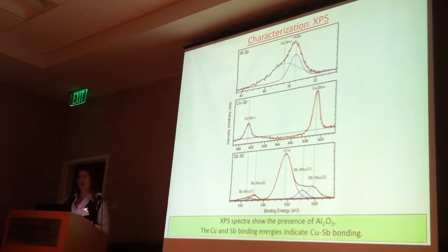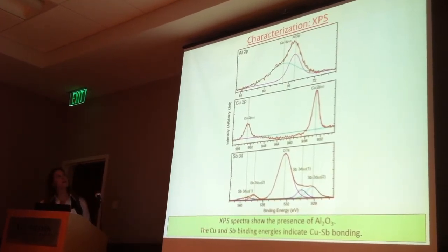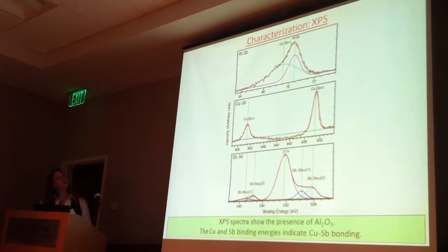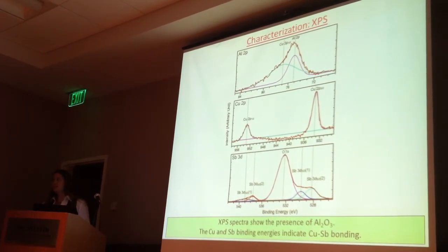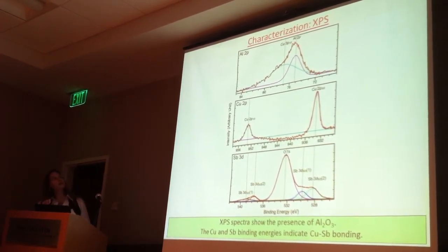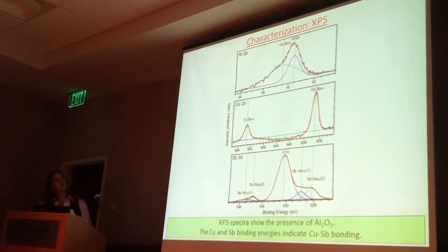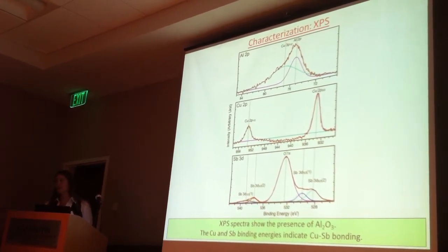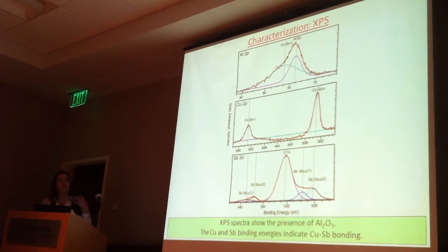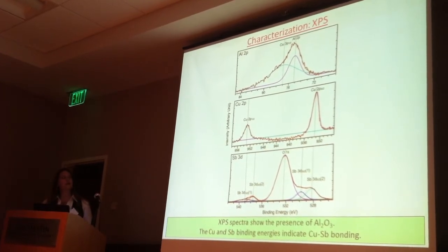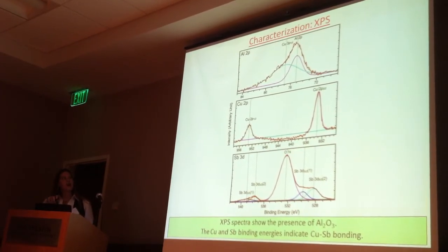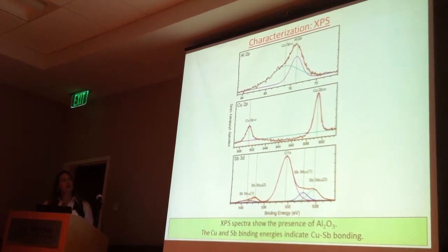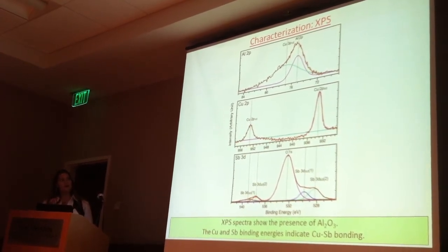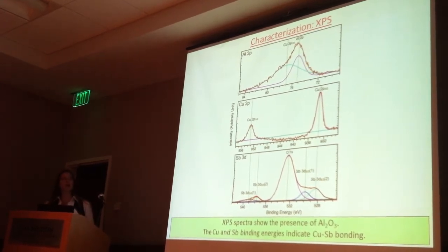So we turned to XPS, and this top graph here is the aluminum spectra for XPS, and this peak right here is for aluminum, and the binding energy does correspond to aluminum oxide. So we found, yes, we do have aluminum oxide in our material. And when we looked at the spectra for copper, we found that the shape of these peaks is more like copper metal, not like copper oxide.